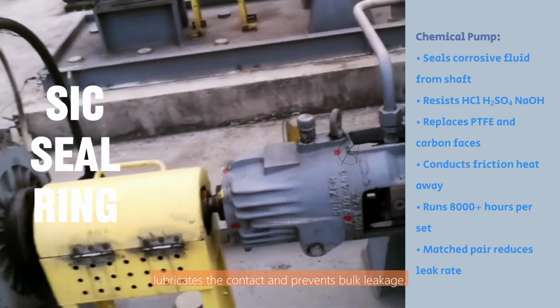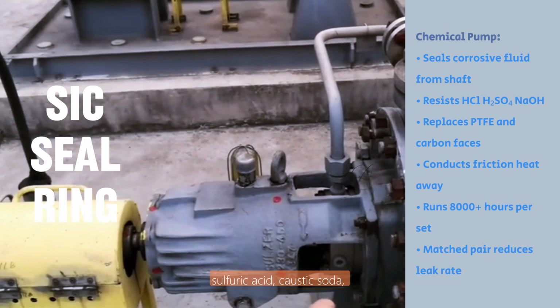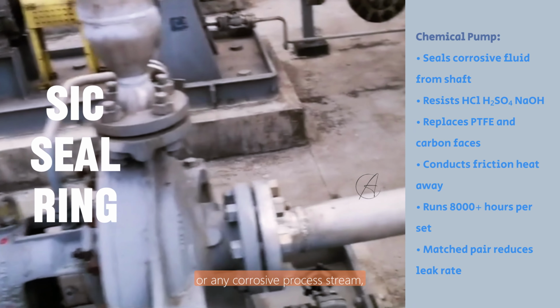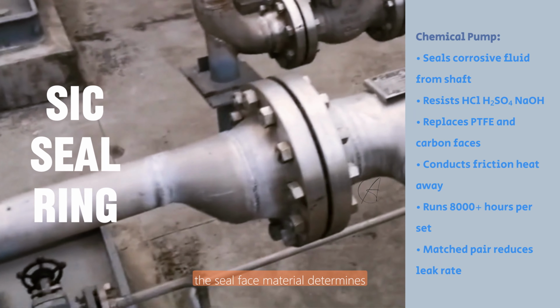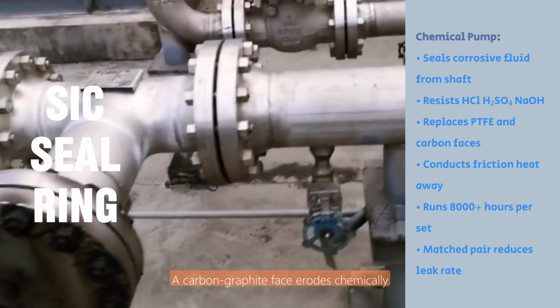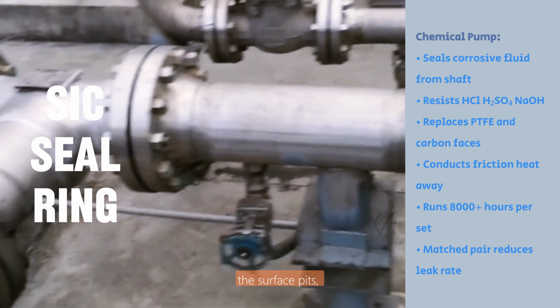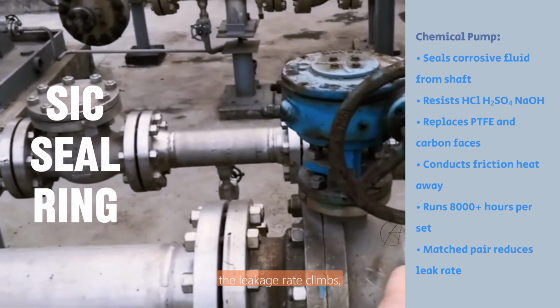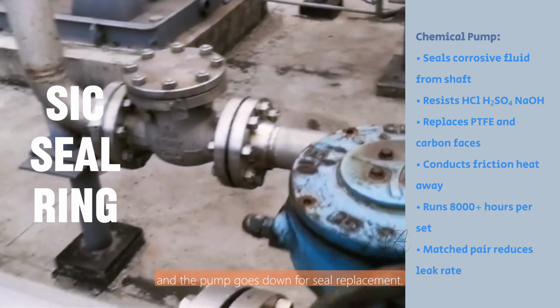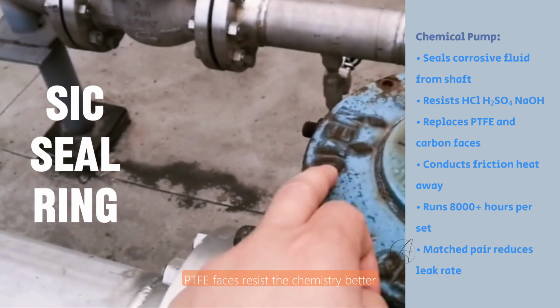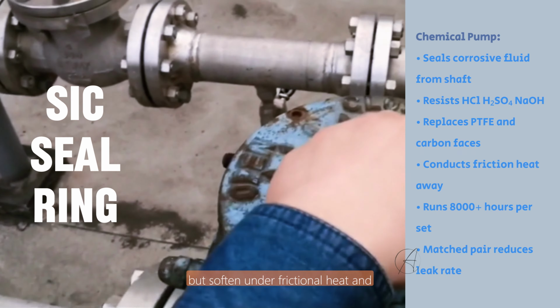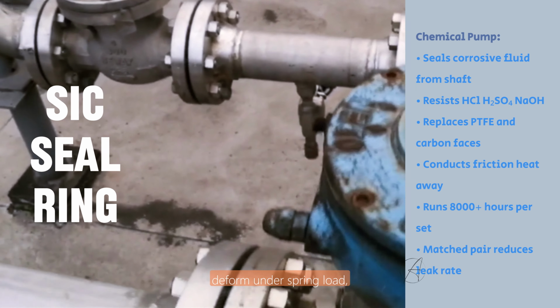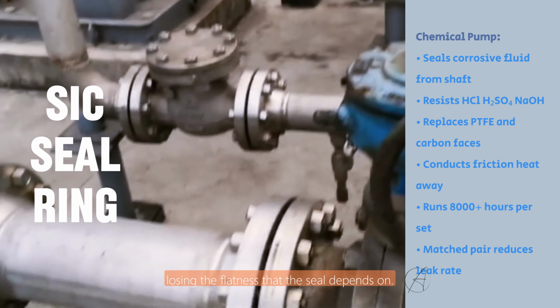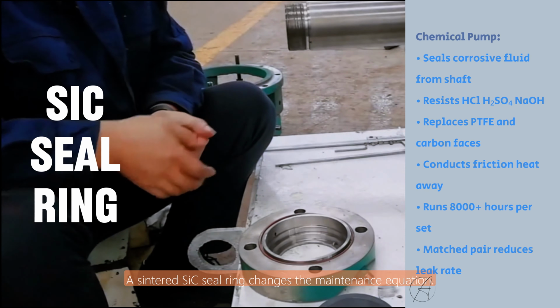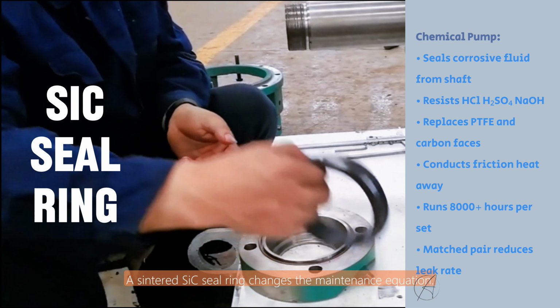In a plant pumping hydrochloric acid, sulfuric acid, caustic soda, or any corrosive process stream, the seal face material determines how long that barrier holds. A carbon graphite face erodes chemically and wears mechanically. The surface pits, the flatness degrades, the leakage rate climbs, and the pump goes down for seal replacement. PTFE faces resist the chemistry better but soften under frictional heat and deform under spring load, losing the flatness that the seal depends on. A sintered silicon carbide seal ring changes the maintenance equation.